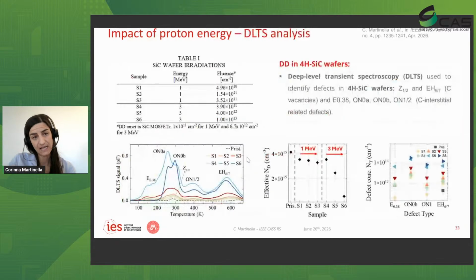We did the same experiment also irradiating wafers. We had 4H silicon carbide wafers. 3 were irradiated with 1 MeV protons and 3 with 3 MeV protons. The first were irradiated below the onset for displacement damage.